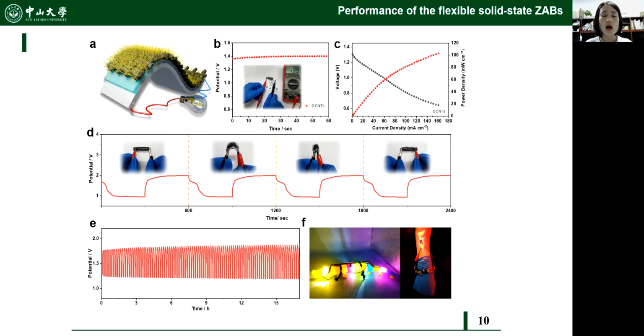We also designed a highly flexible all-solid-state ZAB by assembling zinc and OCNTs with PAA hydrogel electrolytes. Both the output voltage of 1.39 volts and the power density of 103 milliwatts per square centimeter of the battery are slightly lower than those of the liquid ones, but still higher than most recently reported all-solid-state ZABs.